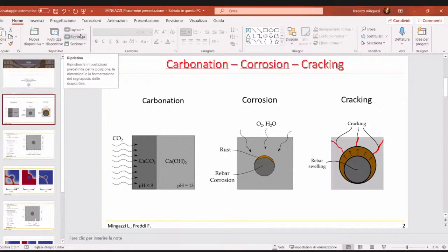The main effect which concerns the corrosion process is the change in the pH of the material, which starts for the hydrated concrete at high value around 13 and lowers to more neutral values, which lead to the depassivation of the steel rebars. The depassivation of steel rebars leads to a consequent rust formation and a swelling phenomenon into the concrete, which has been modeled via the electrochemical equation. And we obtain, therefore, the swelling of the steel rebar due to the rust formation, which has been used as a loading parameter for the mechanical problem.